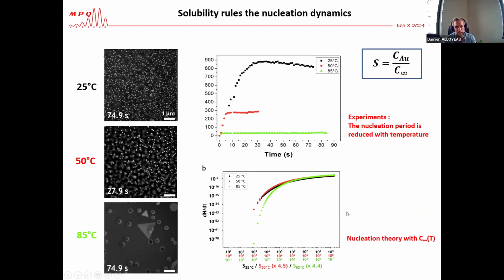And now we can revisit the nucleation theory and understand why the nucleation period is shortened when the temperature increases, simply because you have a change in the solubility of your solution. So we were very happy to be able to bring new information to the nucleation theory, but the idea of observing is really to go beyond the LSW theory.